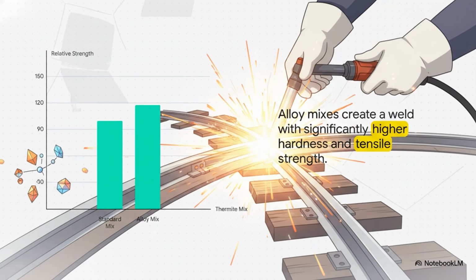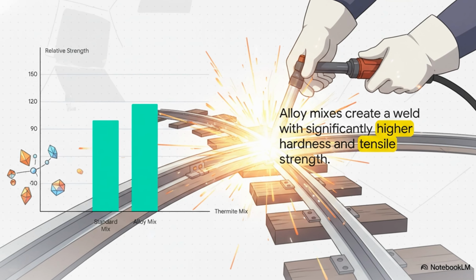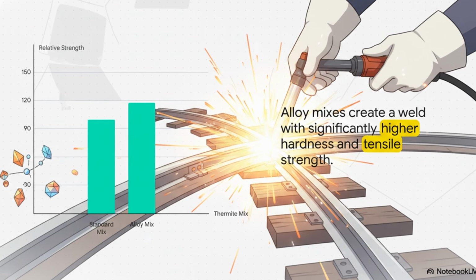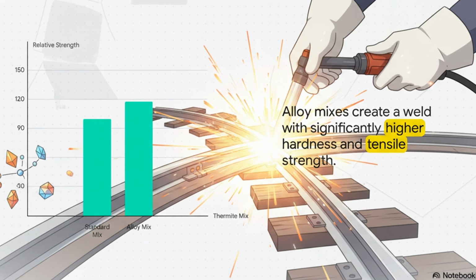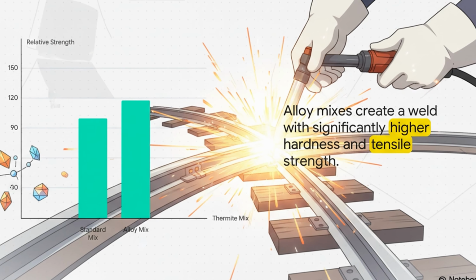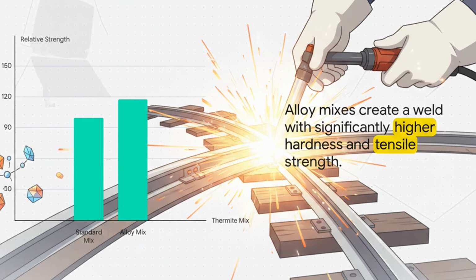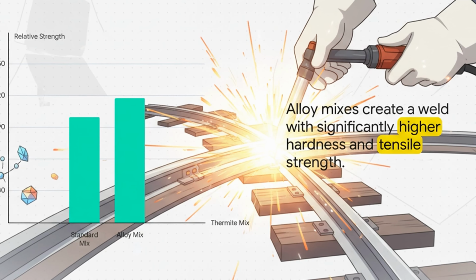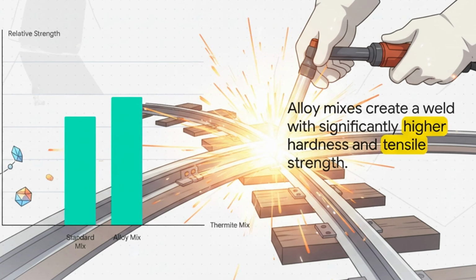And the difference is huge. You can see right here, these alloy mixes give you a weld with much higher hardness and much greater tensile strength. Now, there is a trade-off. You lose a little bit of flexibility, but for those really high-stress tracks, that extra strength is completely non-negotiable.